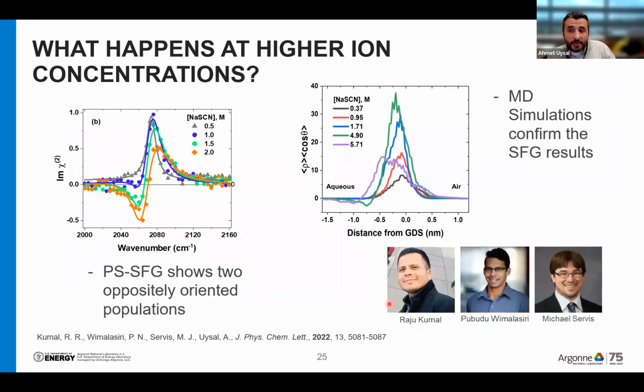Our hypothesis about why that PPP signal was going down with increasing bulk concentration was actually correct after studying the system with phase-sensitive SFG. Now we can measure the imaginary chi2 directly from phase-sensitive measurements, and what we see is this negative peak corresponds to a new population appearing with the opposite orientation. And as you can see, this is happening right after 1 molar concentration, when we start seeing the decrease in the classical SFG signal.